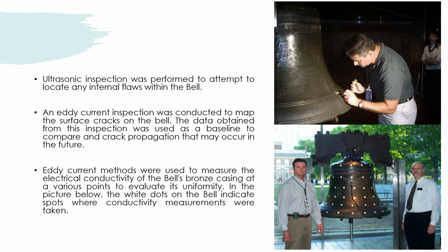Next, an eddy current inspection was conducted to map the surface cracks on the bell, and the data obtained from this inspection was used as a baseline to compare against crack propagation that may occur in the future.